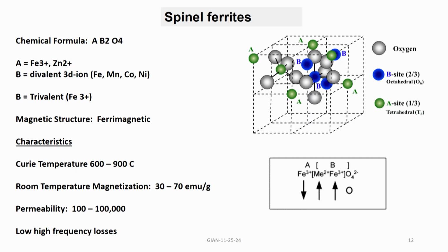So, in the case of all the spinel ferrites, the larger ions such as zinc always tend to occupy the tetrahedral site, whereas the octahedral site is occupied by iron 3 plus and any divalent substitution such as manganese, cobalt and nickel. So, the magnetic structure is, you have iron 3 plus also in the tetrahedral or A site, and they are oriented in the direction opposite to the magnetic moment in the octahedral site.